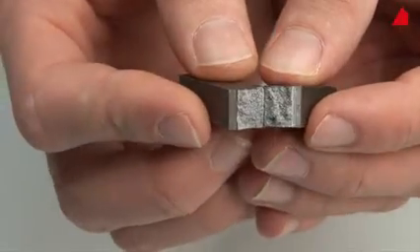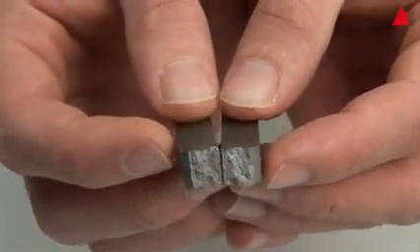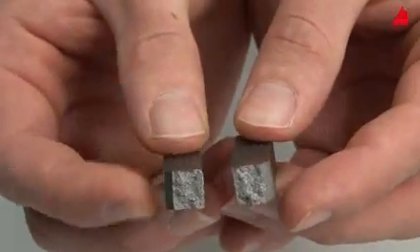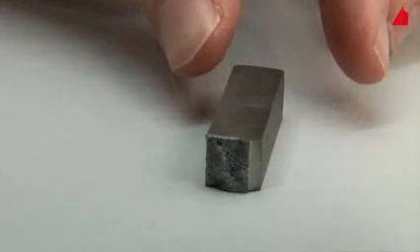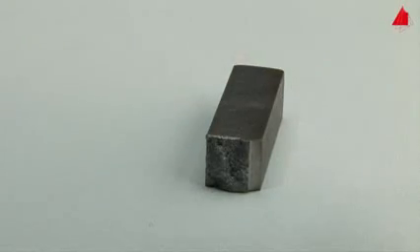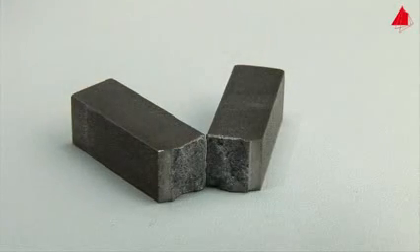The first specimen only shows very little plastic deformation. A mostly flat, slightly glittering fracture surface has been formed. This is an important indication that this kind of steel is only able to absorb small amounts of notch impact energy. It shows mainly brittle behavior due to the strain aging effect.